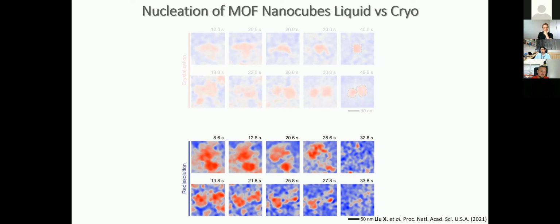Because you're not tracking individual particles or individual occurrences of dense regions. Here you can really identify, and this is important because this is the attempt rate to form a crystal, and the number of the failed attempts actually determines your nucleation rate, right? So if you understand how crystals form, then you can predict the nucleation rates. For most of the models based on classical nucleation, there is a gross discrepancy between the nucleation rates they predict and the experimentally observed ones. So understanding how this process actually flows can enable you to understand the whole nucleation much better.